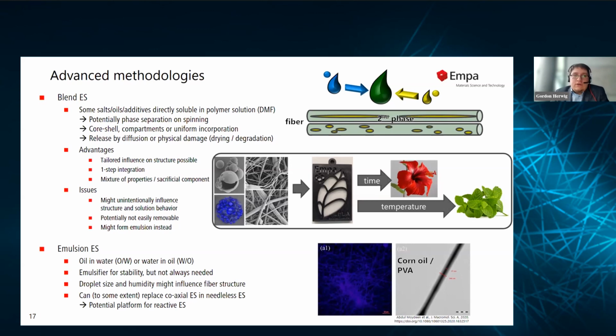Sure. I mean, it depends entirely on exactly what solvent you're using because there are different flash points. The flash point is always measured, I don't know if you've ever seen these flash cup tests, directly on an open cup where the solvent is basically evaporating directly from the cup and then there's a flame going over it to try to ignite it. We don't really have that situation in the Nanospider because we have this little wire that basically completely dries up, or maybe not, depending on how quickly your shipper runs over it. And you don't have enough material that you can actually have a proper explosion or flammability risk. Yes, you can have sparks or something like this, but if it's so dilute and the airflow constantly gets rid of it, the risk is minimal to non-existent.